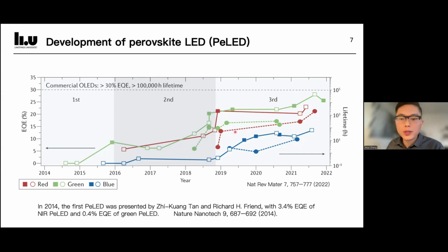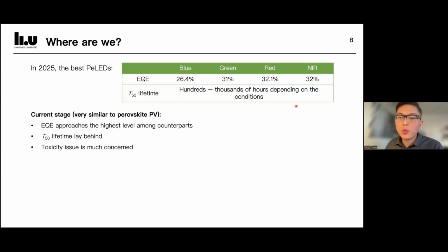And just for reference, the dashed line shows the benchmark for the commercial OLED. They almost exceed 30% EQE, and the lifetime exceeds 100,000 hours.